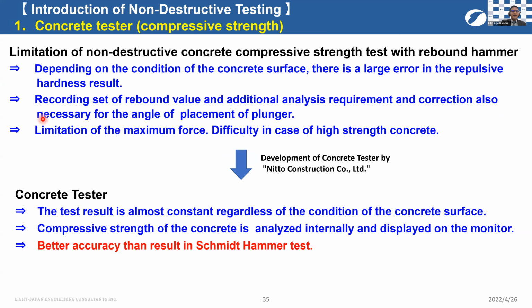Likewise, the rebound hammer had to measure a set of rebound values and calculate the compressive strength by test work. Even correction is also necessary for angle of placement of the plunger. In case of the concrete tester, the compressive strength of concrete is analyzed internally and displayed on the monitor automatically. So this saves time for both on-site work and desk work, obviously.